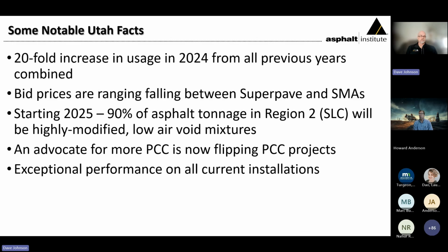Some notable facts. We have seen a huge increase in the tonnage. About a 20-fold increase was planned in 24, and as we already mentioned, some of that is carrying over to 25. That is looking at what had happened in years 21, 22, and 23 compared to 24. Average bid prices are typically falling between Superpave and SMA. And as Howard mentioned, the contractors are very encouraged and supportive of this mixture. They are offering value engineering proposals to the state of Utah, which are commonly accepted, switching SMA projects to this material.